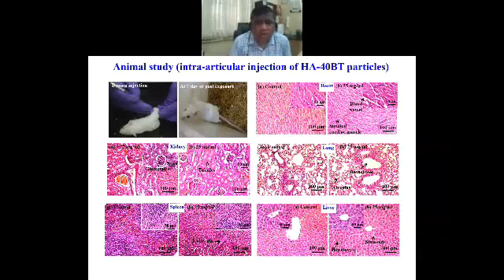And after a few days, or let's say 2 weeks of study, we took histology sections of the different vital organs to see whether there was any signature of toxicity, whether tissue architecture in different vital organs was significantly changed. These vital organs are liver, lung, kidney, heart, and also spleen. And we did not see any signature of toxicity from the hydroxyapatite 40% barium titanate particles.